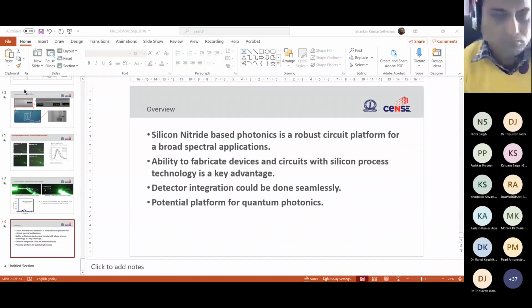We have two types of nitrides. One is deposited using a furnace, low pressure chemical vapor deposition, and the other nitride comes from plasma enhanced chemical vapor deposition. And they are at two different temperatures. One is done at 780 degrees Celsius. The other one is about 350 degrees Celsius. So the temperature budget for these two processes is very different. However, both end up as amorphous, but the stoichiometry is very different. One has high hydrogen content while the other does not. So the material depends on how you deposit.